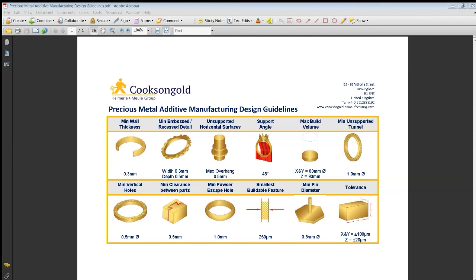The minimum clearance between two parts is 0.5 millimeters. So if you are creating a mesh or a bracelet or links, make sure there's 0.5 millimeters in between each part, only because if they're touching, they will then weld together and there won't be any flexibility potentially. The minimum powder escape hole, as we said earlier, is 1 millimeter, so we can remove all the powder from inside a hollow part.